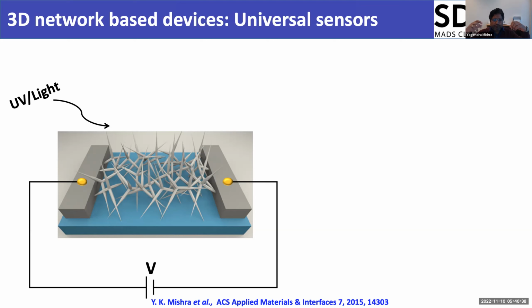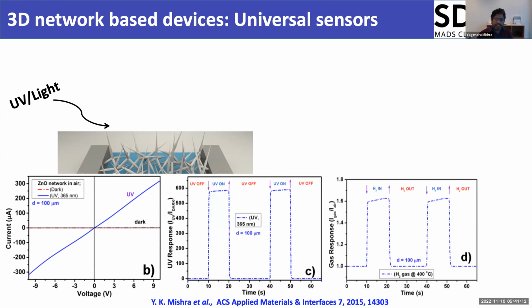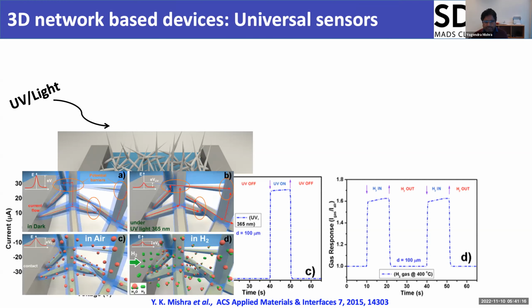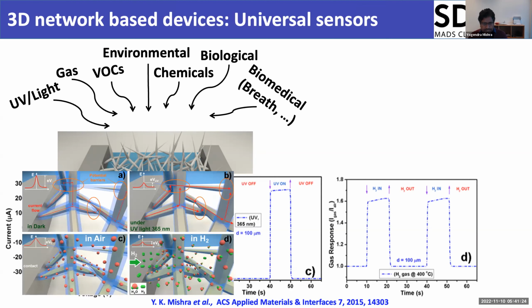In thin film based sensing and nanowire based sensing, we have a challenge of how to integrate them, and the surface is not fully accessible. We came up with the idea of designing a network based sensor, like a slab. In this, we have very nice surface accessibility. We can deposit electrodes at both ends and easily make a device. We tested this for UV light, and for gases, hydrogen. We understood clearly the mechanism that the sensing is mainly due to the increase or decrease in the width of the conduction channels. Then we went further to gases, VOCs, environmental and chemical sensing.